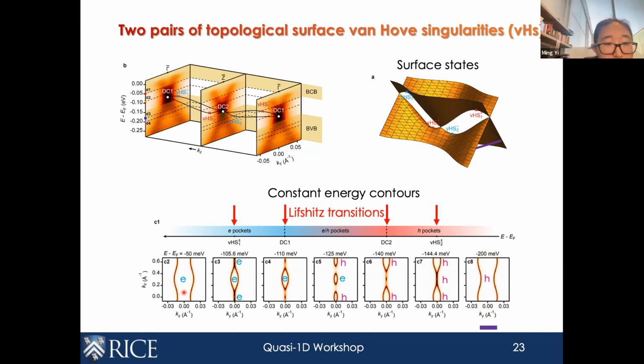So this shows that this topological surface state will be very interesting because we can give rise to a number of Lifshitz transitions. Not only that, experimentally this would be feasible because these features are completely exposed within a global band gap, which means that they will be accessible by transport, by STM and other probes. And furthermore, they live really, really close to the Fermi level, and you can imagine with electrostatic gating or chemical doping, one can at least achieve